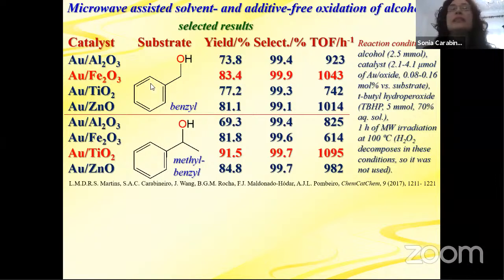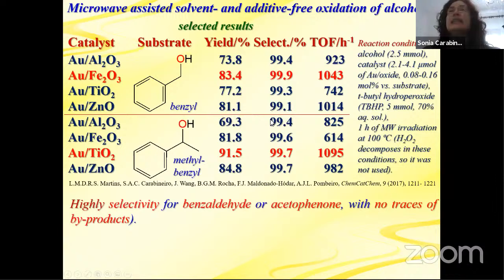So you obtain these results here for the benzyl alcohol oxidation and for the methyl benzyl alcohol oxidation. The best ones here were iron oxide, gold on iron oxide, and here gold on titanium dioxide. We can see that very high selectivities were obtained, above 99% for both benzaldehyde here and here for acetophenone, with no traces of byproducts.